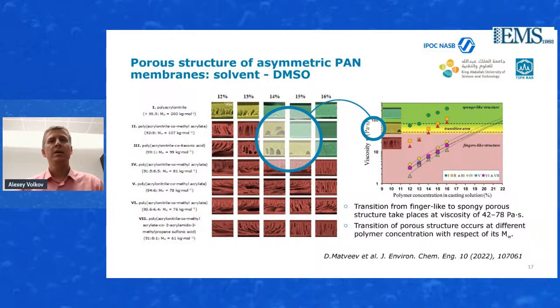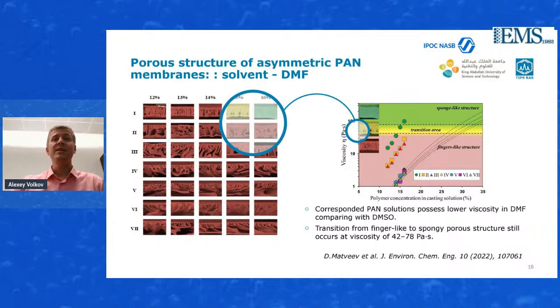It means that if we'd like to get a different morphology, we don't need to go to different polymers. We can stick with the same polymer like PAN, and based on the viscosity and the molecular weight of the polymer, we can adjust the concentration to reach the threshold value of viscosity to go for the finger-like or sponge-like structure. But more interestingly, if we replace the solvent with DMF, we will get mostly finger-like structures, because DMF solutions have lower viscosity. And if you're thinking about how to get the sponge-like structure with your polymer, try to use more viscous solutions or add additives to increase the viscosity, and then you will get the sponge-like